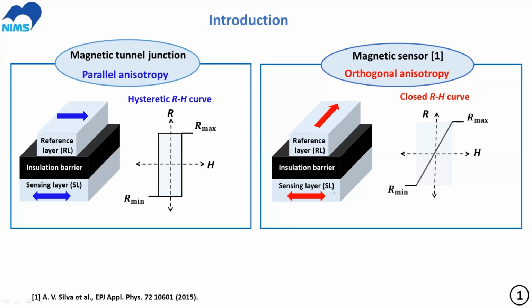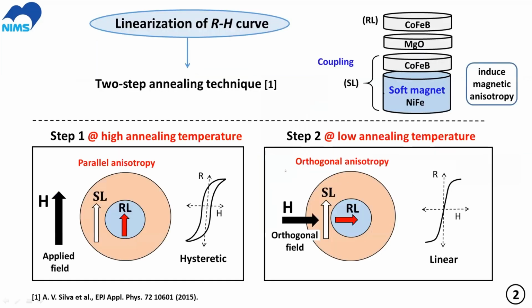Actually, there are a lot of strategies or linearization techniques reported in the literature in order to get this kind of linear transfer curve. Personally, I like the two-step annealing technique, simply because it produces a very linear and hysteresis-free curve. It means you can produce a very low noise sensor. But it needs some tricky points regarding the annealing and microfabrication, and I'm going to talk about them one by one. Firstly, let's start with the annealing technique.